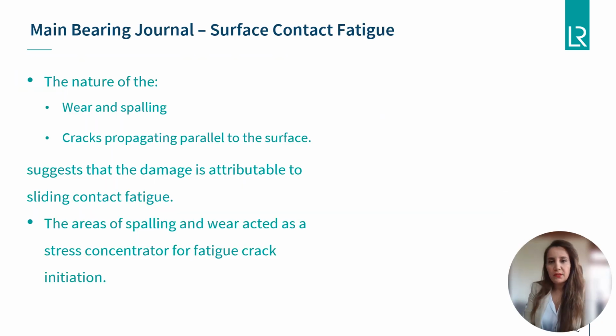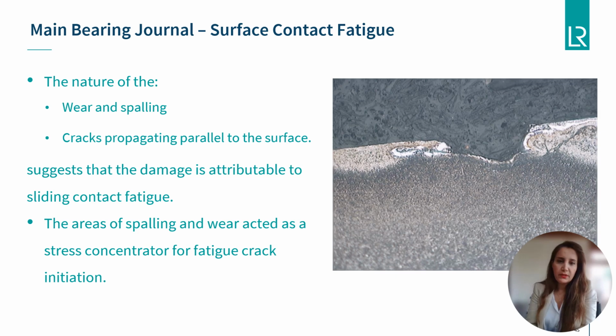The nature of the spalling observed may suggest that the damage is attributable to surface or sliding contact fatigue. Sliding contact fatigue is commonly found in components that slide against each other under high contact pressure and which are susceptible to development of surface pits or spalls. It is thought that the spalling damage acted as a stress concentrator for fatigue crack initiation.